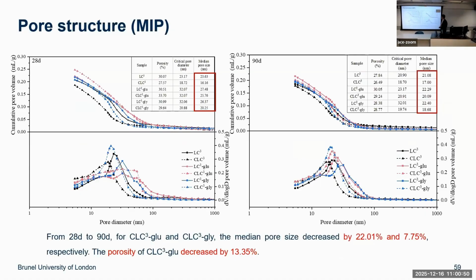We also further look at the pore structures. It was mentioned that we want many more non-deleterious pores, which have particle size less than 50 nanometers. So we look at the median pore size and critical pore size with different formulations at 28 days and 90 days. From carbonated LC3 with glutamic and carbonated LC3 with glycine, the median pore size decreases by 22% or 8% compared to the reference, and the porosity also decreases.